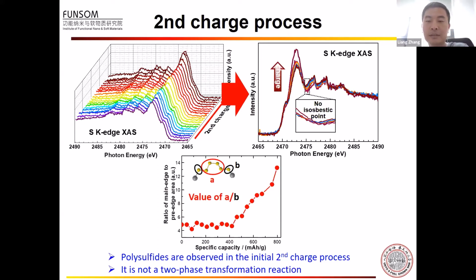Because for the lithium polysulfide and the elemental sulfur, the main feature is overlapped, we cannot distinguish the elemental sulfur from lithium polysulfide. Therefore, we use the area ratio between the neutral sulfur and the charged sulfur in polysulfide as a proxy of the average length of the polysulfide. We can see here the area ratio doesn't change very much at the beginning and then increases fast.